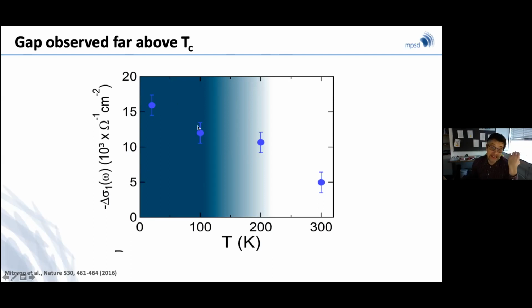In fact, a gap that is even larger than the one that I open at equilibrium, all the way to 100 plus Kelvin. And then I still have a finite gap all the way to 300 Kelvin and higher, except that somehow this gap is only a partial gap. And my degree of certainty when I say that these properties are superconducting-like decreases with the amount of blue that I've put in this plot. So although there is an increasing mobility at all these frequencies, I would argue that the bluish states are the ones where the equivalency with the optical properties of the equilibrium superconductors can be established.